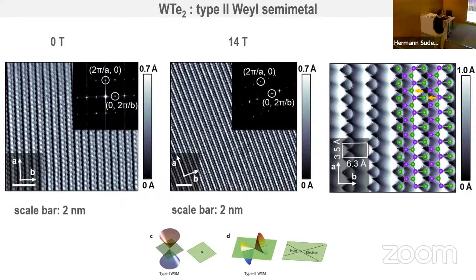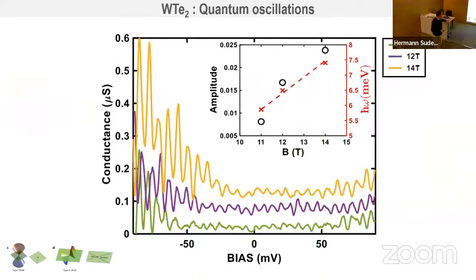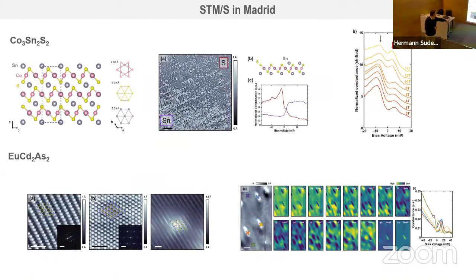And we are measuring many different systems. So this is a type 2 Weyl semi-metal, and it has a Weyl cone, and it also shows Landau oscillations. So you have a parabolic band, you apply a magnetic field, you get quantization because of the circular motion of the electrons, and this quantization gives you these peaks, and you can follow them and relate this to the properties of the Weyl nodes. And this is a very nice system. It's a magnetic Weyl semi-metal.